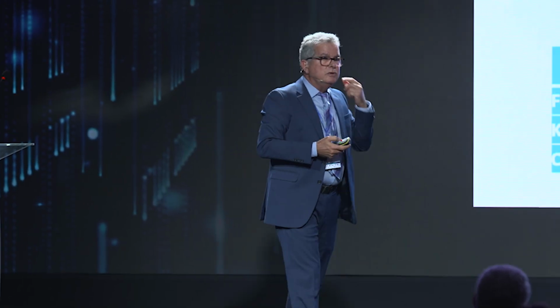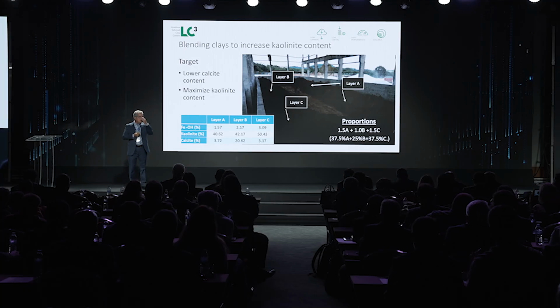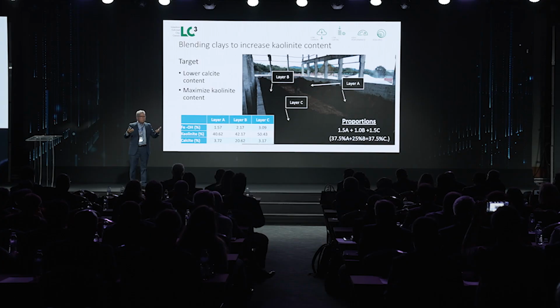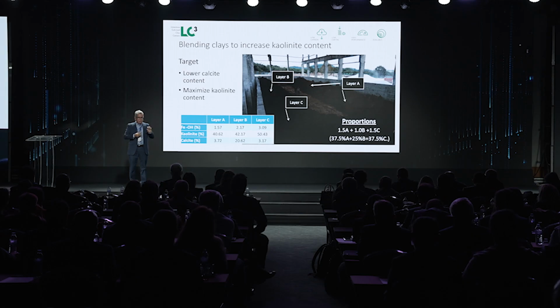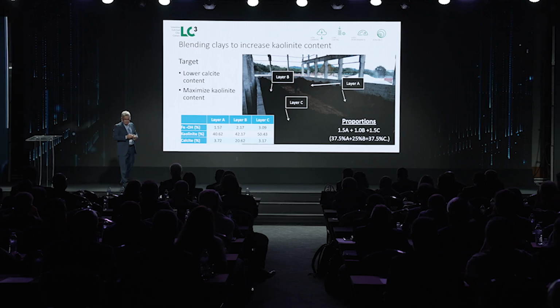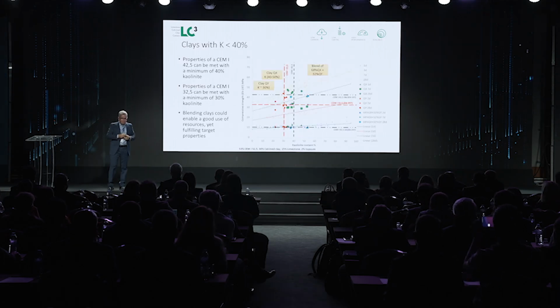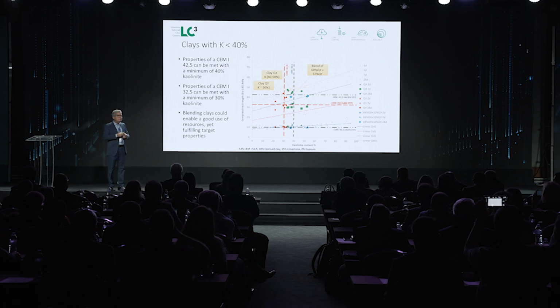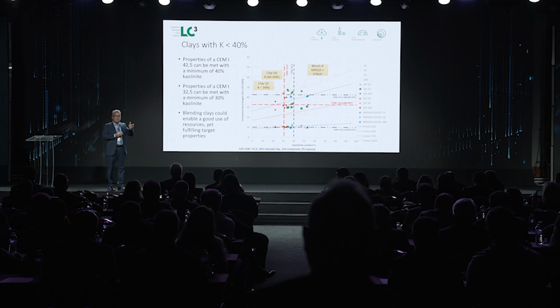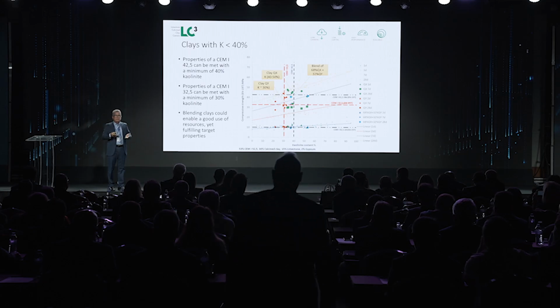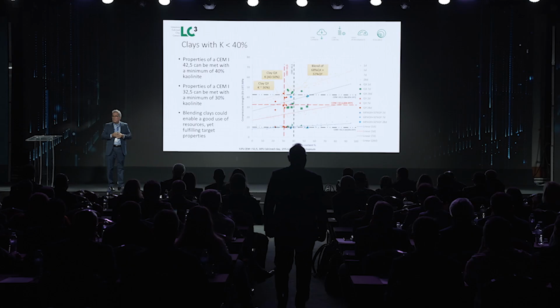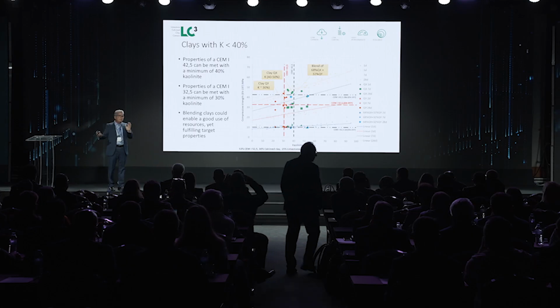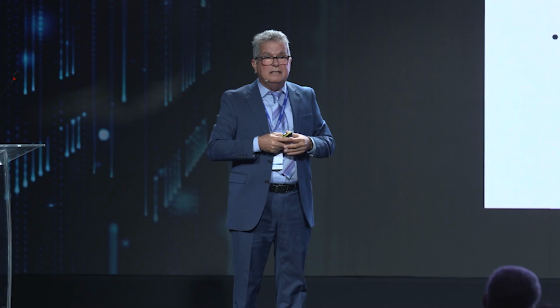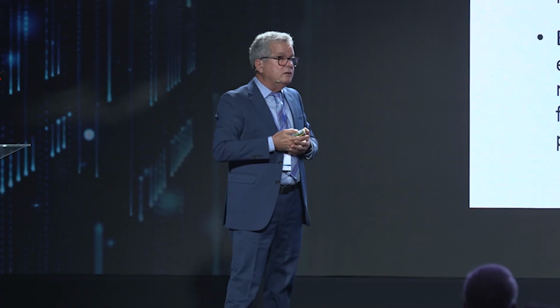One of the things that we are doing more and more, this is also an industrial trial we ran a few years back, is to understand the clay deposit and to blend different clay types in order to target the optimal kaolinite content and minimize, for instance, limestone and others. This is an example of work we were doing in Africa, in Angola, for the company Cimangola. They had clay in their own factory with a kaolinite content of about 30%, and we were able to find a neighboring quarry where you can blend this clay, and you expand the reserves of material, and also improve the quality of this material.